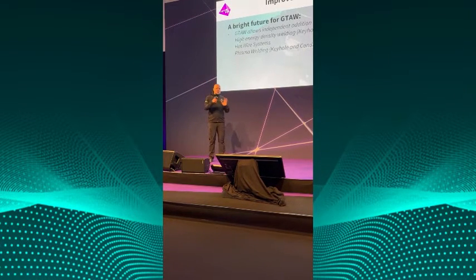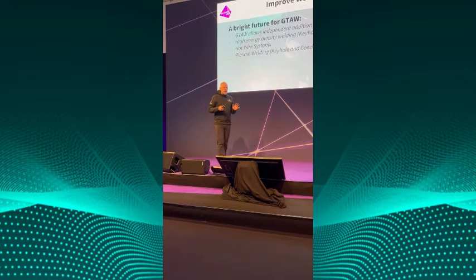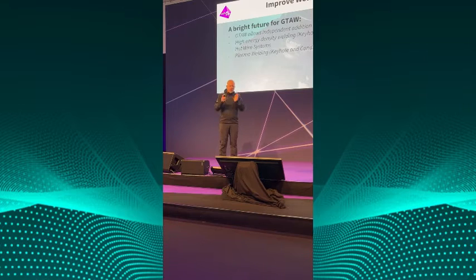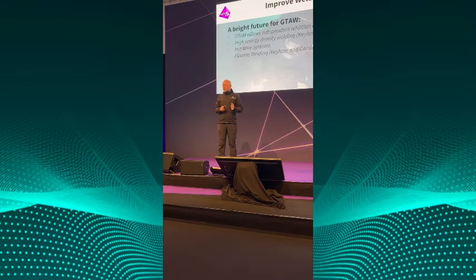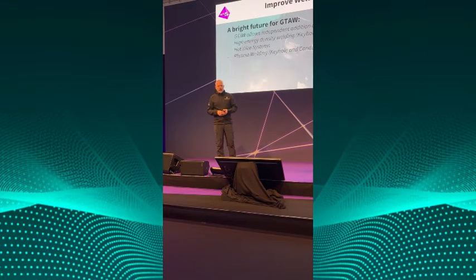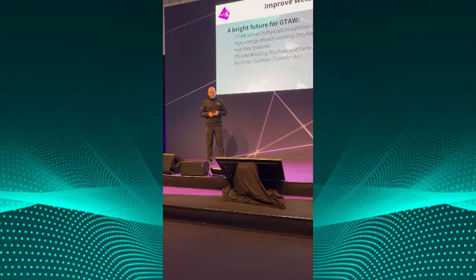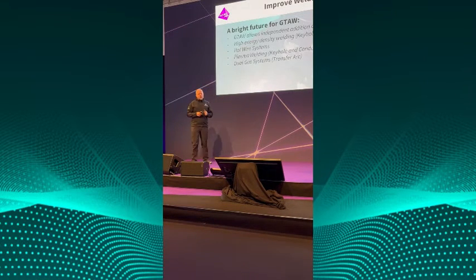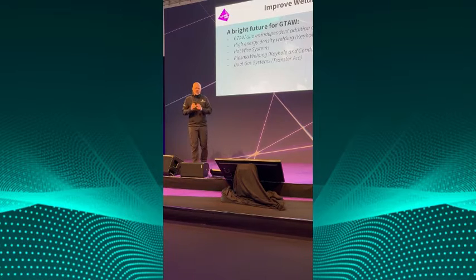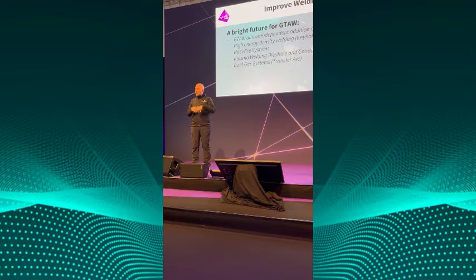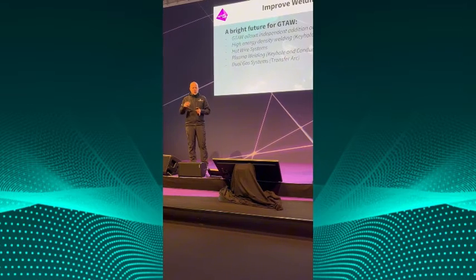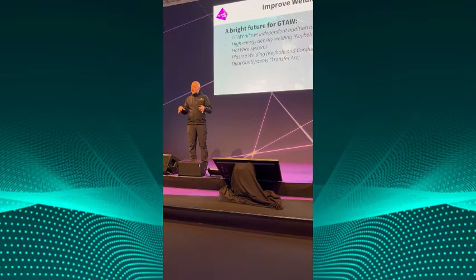Plasma welding, although not directly related to TIG, has in keyhole and conduction mode a fantastic potential to bridge gaps to micro welding and is super reliable. It takes far more training of the welders to manage plasma welding, but I personally think that's a very underappreciated and underused system. I've seen interesting approaches in dual gas systems, so not one single gas nozzle but dual gas nozzles with the transfer arc. So actually a TIG, it's not a plasma process, it's a TIG process, but with a double shielding gas. So the plasma gas and the shielding gas don't have the same composition.